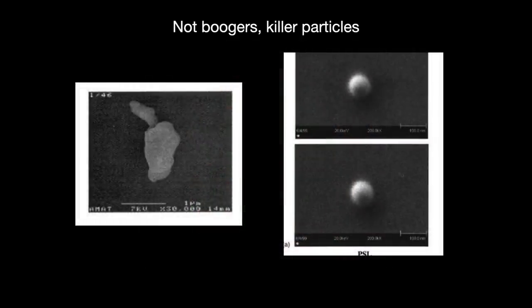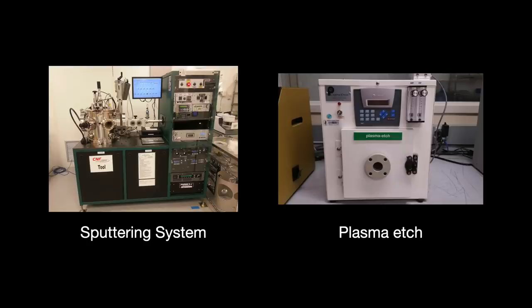There is the concept of killer particles — anything large enough to cause defects in semiconductor production, in the same way dust on a negative causes a visual defect. They can come from anywhere: defects in starting materials or ultra-pure water, for instance. Certain processes like sputtering and plasma etch can generate killer particles too. As process nodes advance, the bar for what defines a killer particle ratchets lower. Recent discussions in the ultra-pure water industry imply a killer particle size under 10 nanometers, roughly the diameter of DNA. These particles can attract static charges, causing additional direct damage to the wafer — electrostatic discharges just 1 to 10 nanoseconds long, but capable of causing melting damage.